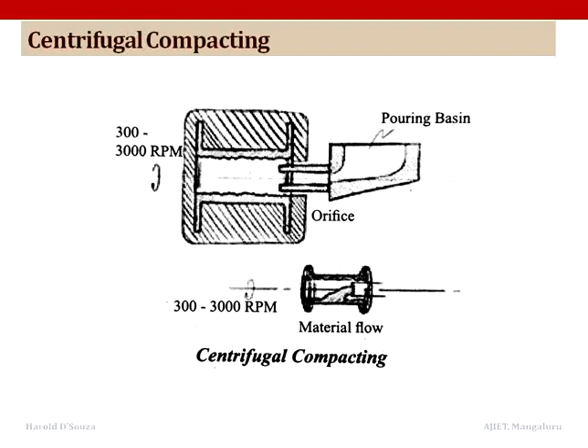Centrifugal compacting. So, here the powder is swirled in the mold and packed uniformly with pressure up to 3 megapascal. The uniform density is obtained as a result of centrifugal force acting on each particle.